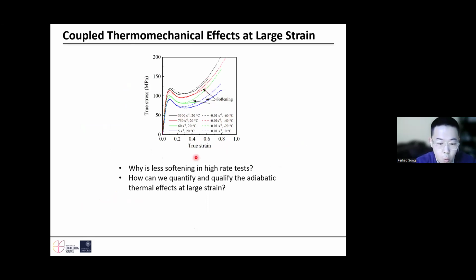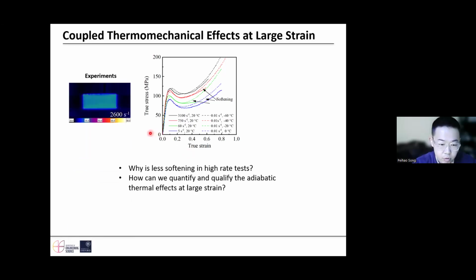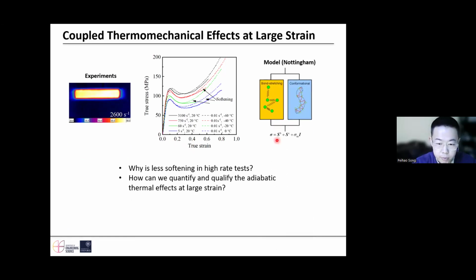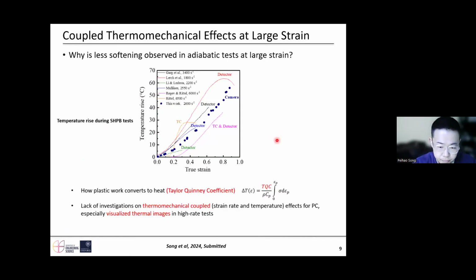To answer why there is less softening in higher rate test, I performed a series of temperature rise measurements during the different loading scenarios and use a model developed by Nottingham team to understand that. The literature measures the temperature rise in the past 2 decades. People mainly use the thermocouple and IR detector to measure that. The biggest drawback of these 2 techniques is they cannot provide a visualized thermal image. So we don't really know what really happened in Hopkinson bar test.